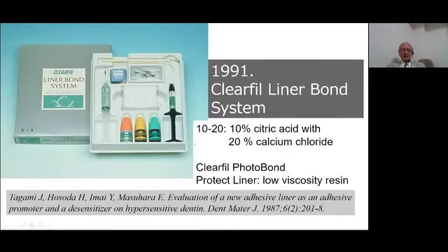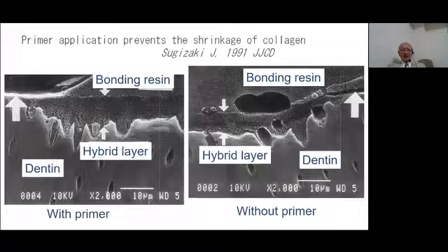By the development of the dentin primer, in this product the dentin primer was here, SA primer, the bonding was very much improved. The function of the primer was seen with this kind of SEM photograph. This is in the case when we apply the primer. This is in the case without primer application. And this is the bond interface. This part is the bonding resin. This is the dentin, and this is the bonding resin. And this is the original dentin surface.